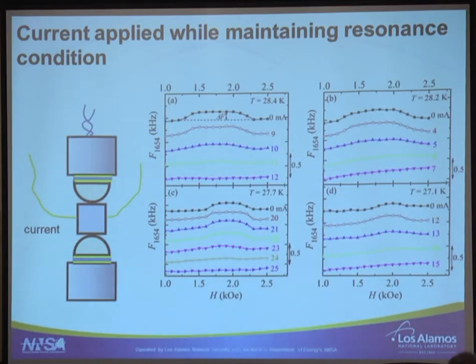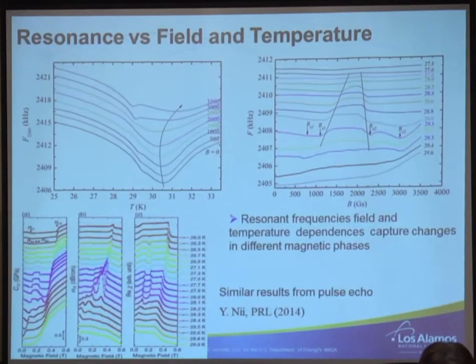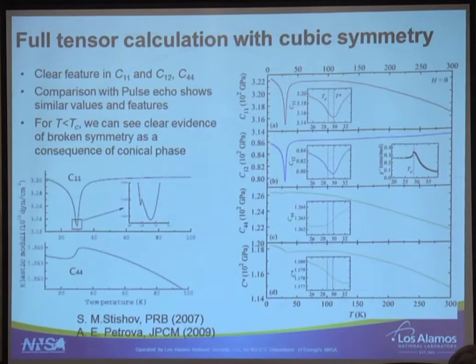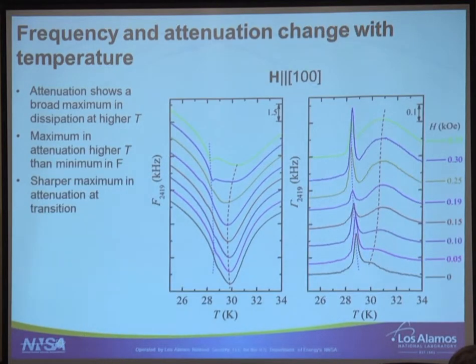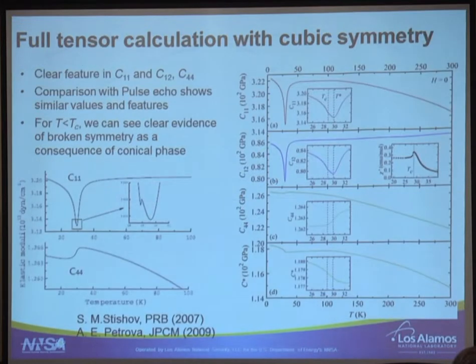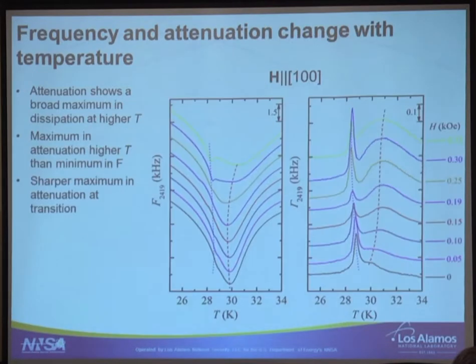In the very beginning, when you showed the temperature dependence, it seems that this fluctuation or this precursor phase has much more influence on the sound velocity than the transition to, let's say, the Skyrmion or the magnetic phase. Yes. Indeed, this is the minimum you see. Let me go to the page here. This is a transition that will go to the extrapolation of the paramagnetic as a function of field transition. This is the effect you see, and this little thing is what you see.